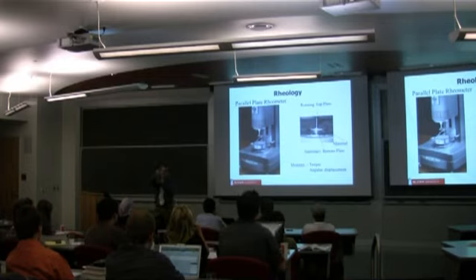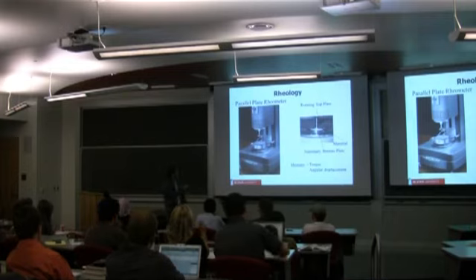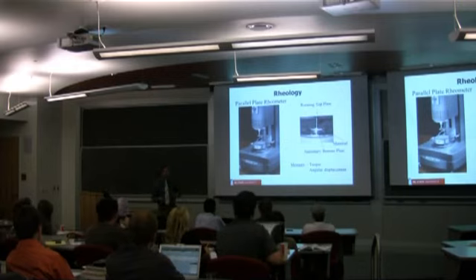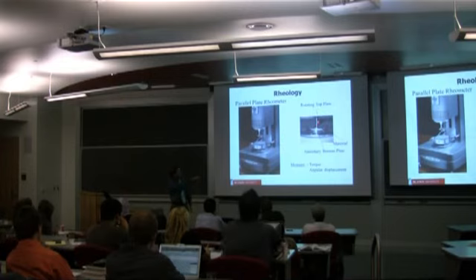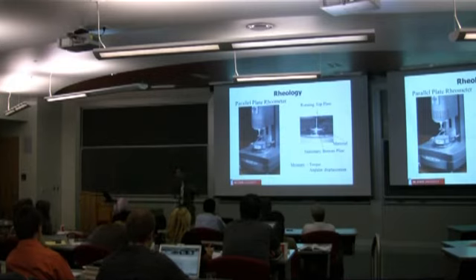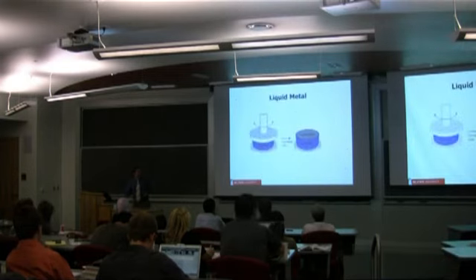And then you bring down another plate, and you squish it, and you measure the torque required to turn the plate back and forth. So you can imagine that if you had water between these plates versus honey or something like that, it's going to be more difficult to turn this plate the more viscous it is or the more elastic it is. And so I like to call this geometry sort of like an Oreo cookie, where the cream of the cookie, in this case, is the liquid metal, and that's really the thing you're trying to measure. But it's a little bit more subtle than that.